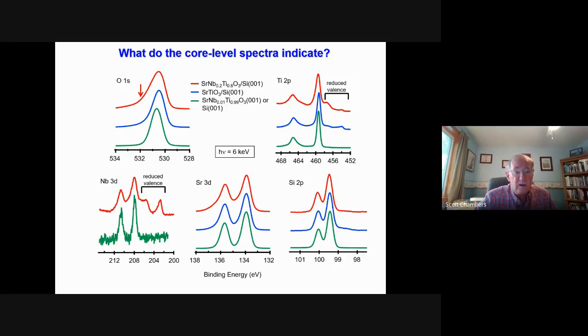Also, you notice that there is an asymmetry on the high binding energy side of all the film peaks, and there is an asymmetric shoulder on the low binding energy side of the silicon. Okay, well, what are you to conclude about this? Well, what you would conclude if you didn't think outside the box on your data is that you have multiple suboxides, which explains the reduced valence on the niobium and the titanium. You would conclude that you had an interfacial silicide because that low binding energy shoulder on the silicon 2p is just at the right binding energy to be titanium silicide. And you would conclude that the asymmetries on the high binding energy sides of the film peaks are due to shakeup, and therefore you have a metallic phase. So in other words, you have a polycrystalline metallic mess.